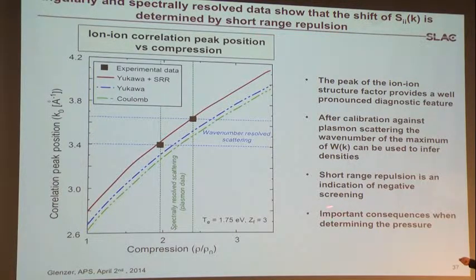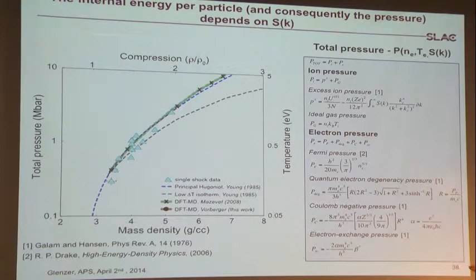These findings have important consequences to derive the physical properties of materials. In this case, we looked into pressure. So these are experimental data. This is the total pressure versus mass density. Those are the single shock Hugoniot data from our experiment. And actually, they follow very nicely a previous empirical known curve published by Dave Young. And also DFT-MD simulations by Mazevet. Those are particle simulations from 2008, and you see there's very good agreement for our single shock data.